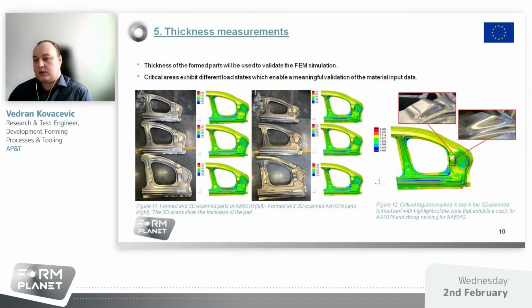After we formed all the parts, we also scanned the formed parts in order to have the sheet thickness information of them. The scans were used to validate the FEM simulation by comparing the sheet thickness of the formed and simulated part. The regions marked in red show a tendency of high thinning, and together with the regions that exhibit a crack for the 7000 and strong necking for the 6000, they can be used for validation.